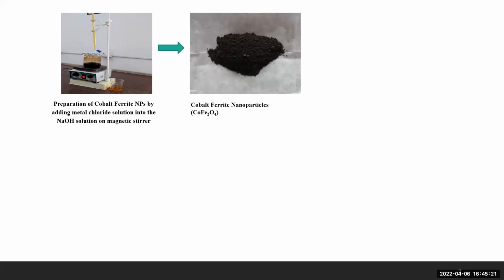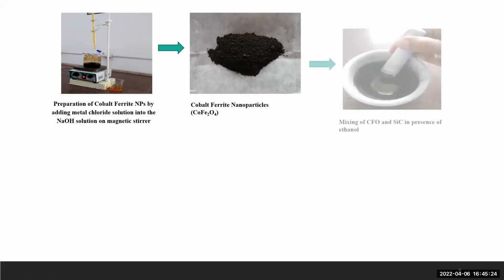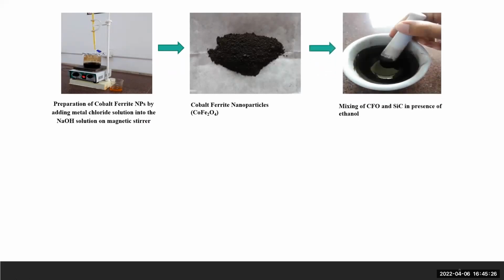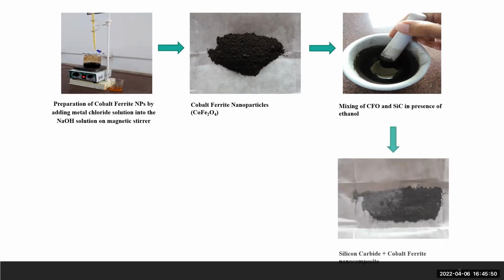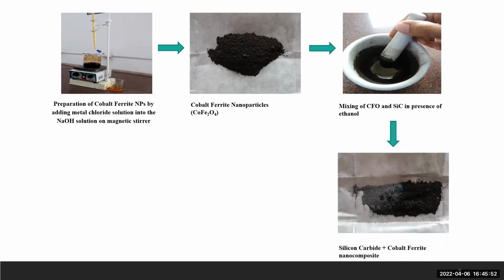Then after getting the cobalt ferrite nanoparticles, we mix the commercially available silicon carbide into the prepared cobalt ferrite nanoparticles using the solid state method. In this method, we have added some ethanol and continued grinding until the evaporation of the ethanol. Then after the evaporation of ethanol, we got the silicon carbide cobalt ferrite nanocomposite in powder form.